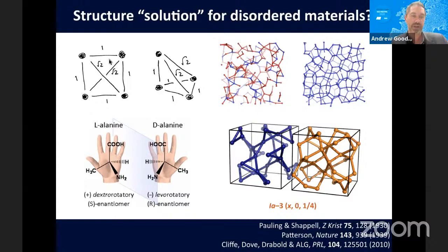So a very simple model here would be if I've got 4 objects arranged at the corners of a square, and I calculate the distances. Here are my pair correlations, 4 at unit length and 2 at root 2. I can construct a different arrangement of those 4 objects, like an equilateral triangle with one above, that has exactly the same set of distances. So in this case, if I couldn't resolve orientation, I'd have no way of distinguishing between these 2 objects. And this, of course, becomes pathological in the case of, say, amorphous materials, where we only have isotropic scattering data. Here's 2 models for amorphous silicon that have exactly the same pair distribution functions, but very different structures and very different higher order correlation functions.